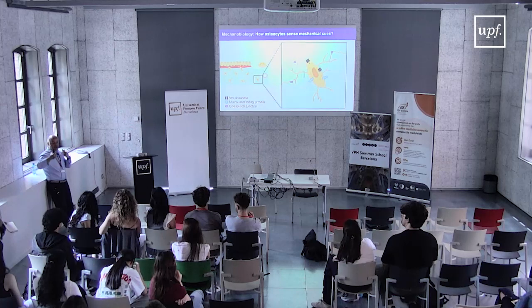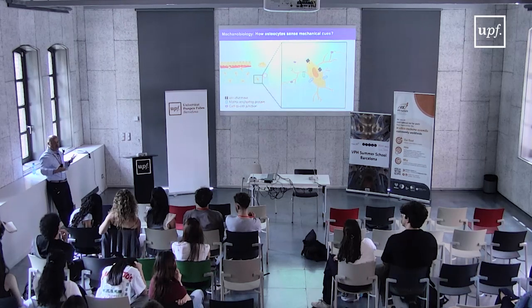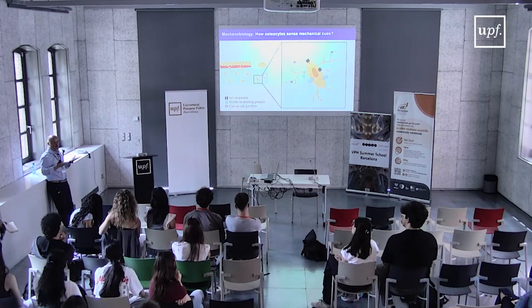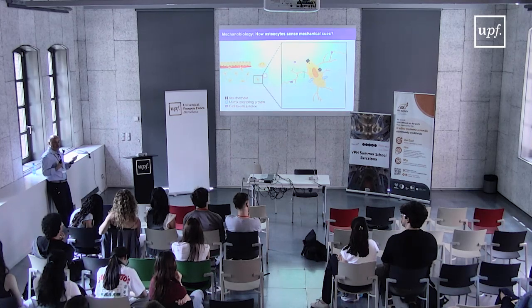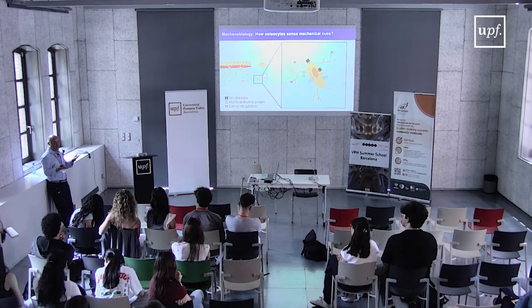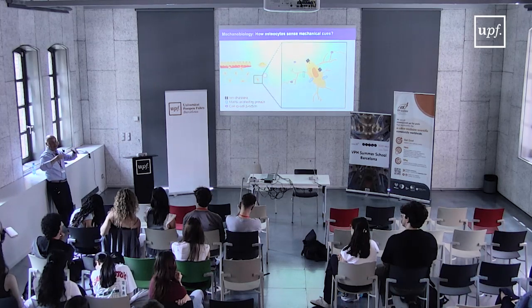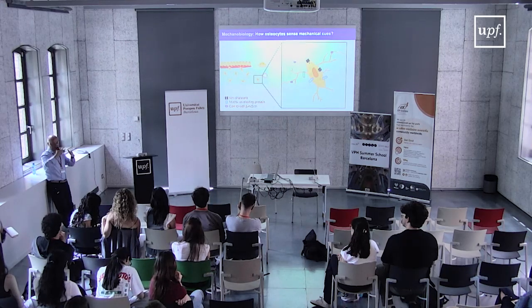But you have to see it as a dynamic process, because the more mechanical stimulation that the osteocyte can sense means that there is a low amount of bone material or a poor bone material quality. So as soon as they secrete an important amount of Wnt3a and they can remodel the cross-linking of the collagen matrix, within minutes they have done that, osteoblasts start to build some bone. So the mechanical sensing for the same mechanical force will be reduced, and they will reduce the amount of Wnt3a, and so on, until they cannot sense the mechanical forces anymore.